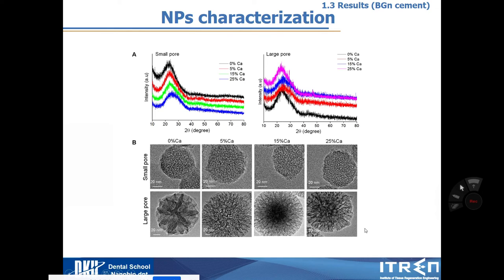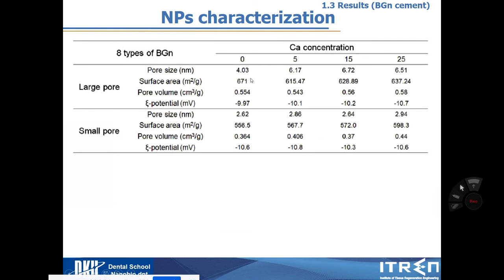And then this is their base morphology revealed by TEM. This large pore has very large pores, you can see, and the small pore has very little dots there. And then this is their typical characteristics as a particle: pore size, area, volume, zeta potential.